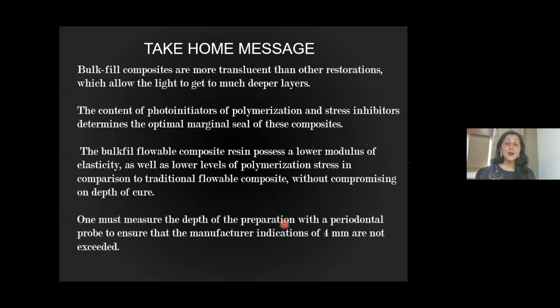And how do you actually do it? Even though I have a feeling for my cavity depth and all that, to be very consistent, I still measure the depth of the cavity, if it's a deep cavity, with a periodontal probe to ensure that the manufacturer's indication of 4 millimeters is not exceeded.